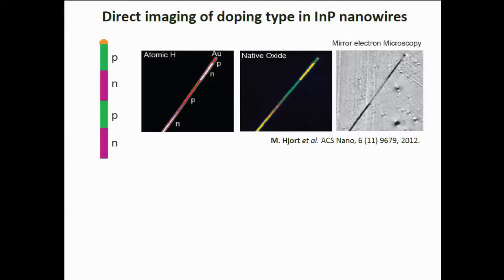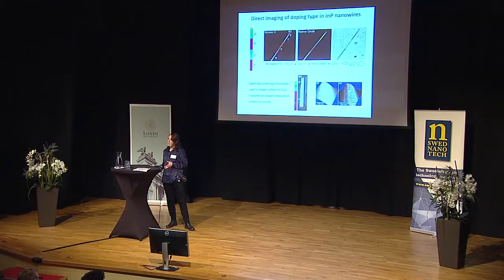This technique has also undergone a variety of improvements over the last few years. We can image much more complicated junction structures, such as a P-N-P-N indium phosphide nanowire, and really image the small gold particle at the end of the nanowire. This technique can now be done with resolutions down to 10 nanometres. Again, we can combine this with STM experiments so that we can get structural information on the surface — how the dopants affect the nanowire growth and what the outside of the nanowire looks like.